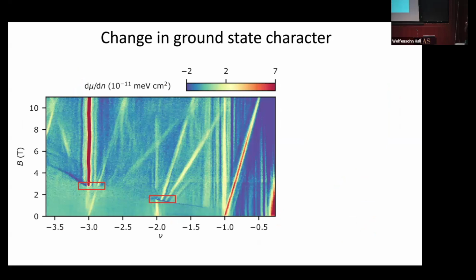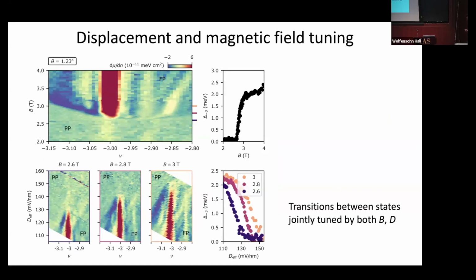I want to come back to this idea of the transition. So these very dark blue lines here correspond to changes in magnetization of the sample. And you can see they have a dramatic change in electronic behavior at filling 2 and around filling 3. So it's clear that changing Moiré bands, just like in the heterobilayer, changing which bands are occupied completely modifies the nature of the ground states that come out.